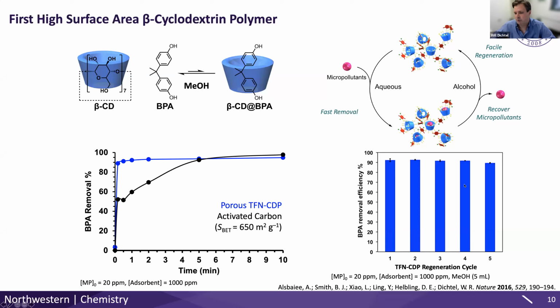So shown here were 5 cycles that we reported in this paper a few years back. And we really see no degradation of the cyclodextrin polymer. Any apparent loss here is just the fact that we're doing a bunch of filtering operations when we were doing this experiment. And so that's really valuable, especially as we start talking about perfluorinated compounds in a few minutes, because the final solution to those is hopefully to degrade them. Just capturing them and removing them and making more contaminated materials is not the most desirable thing.